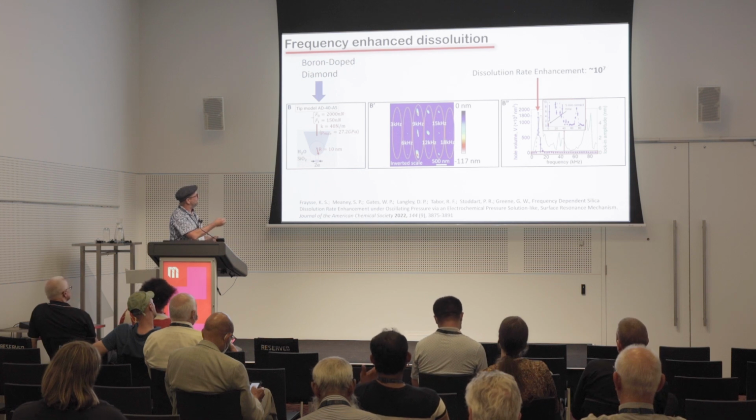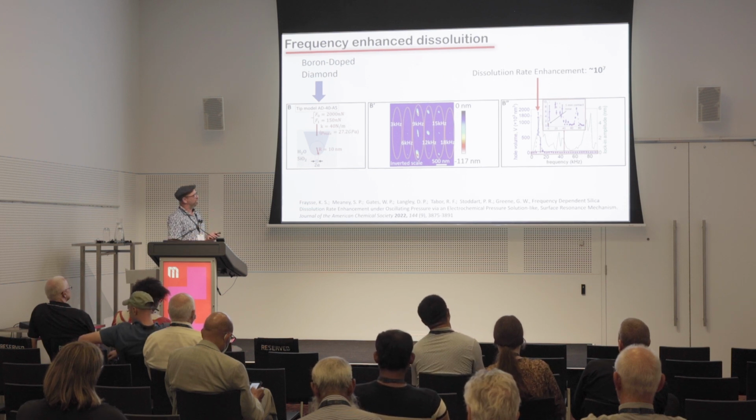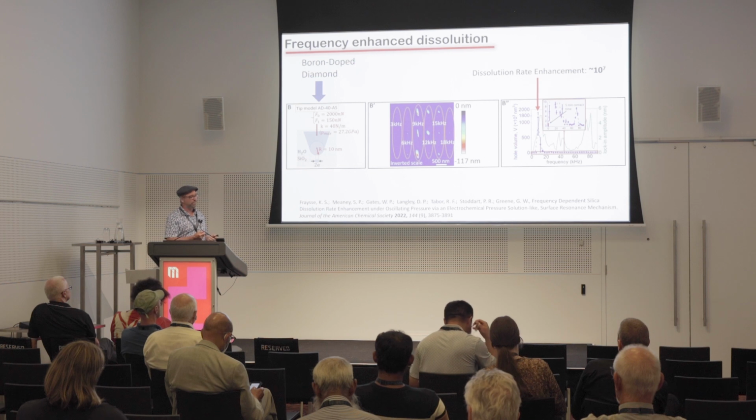So if you keep the set point force and the oscillation amplitude the same, and you vary the frequency, what we saw is actually quite surprising to us, because if you look here, when you oscillate the frequency at 3 kilohertz, you get these tiny dissolution pits.